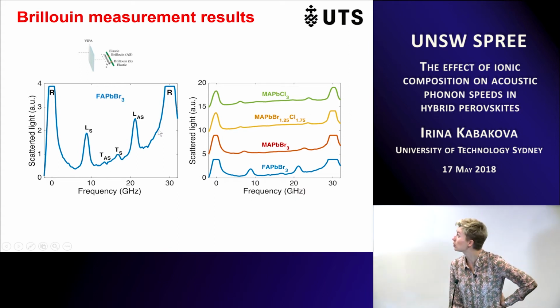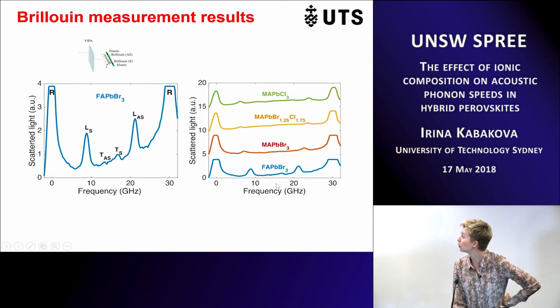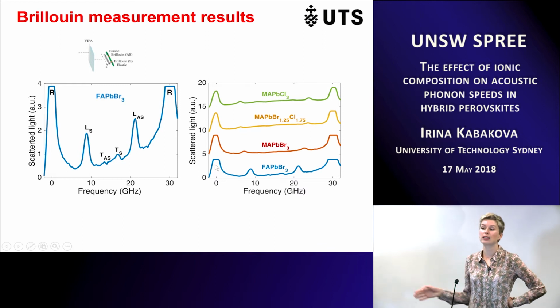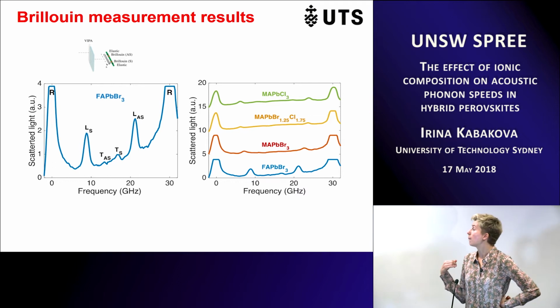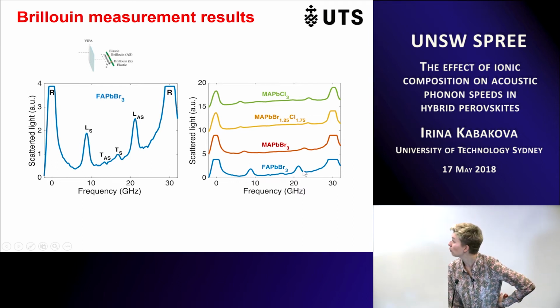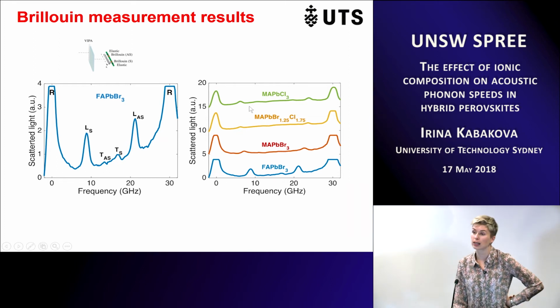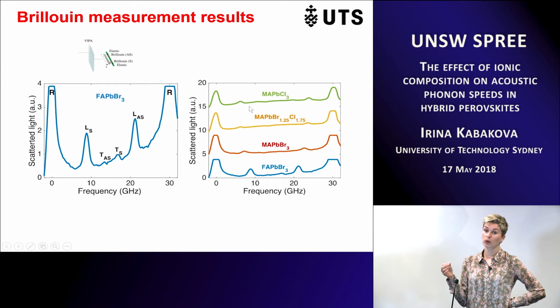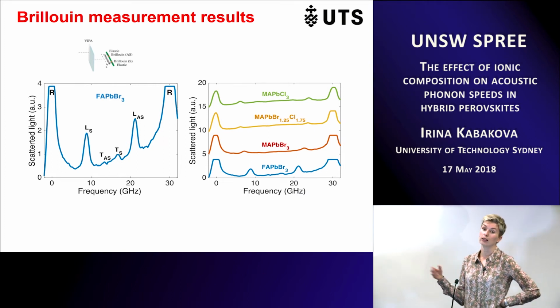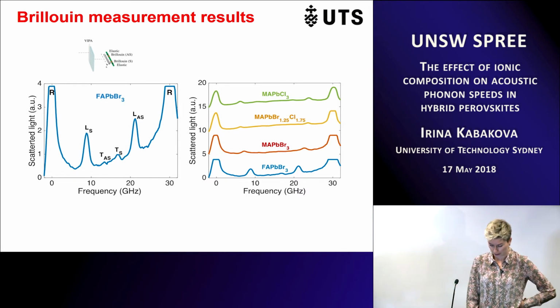And we've done the spectroscopy measurement for all of the crystals, and that's how it looks. What you can already see is that Brillouin peaks are much smaller than Rayleigh, that's for sure, but there's nothing surprising because Brillouin scattering is not a very efficient process. And secondly, you can also see that the location of each peak for each crystal is actually unique. And that's because elasticity for each crystal is unique. It corresponds to the atomic lattice of this crystal.